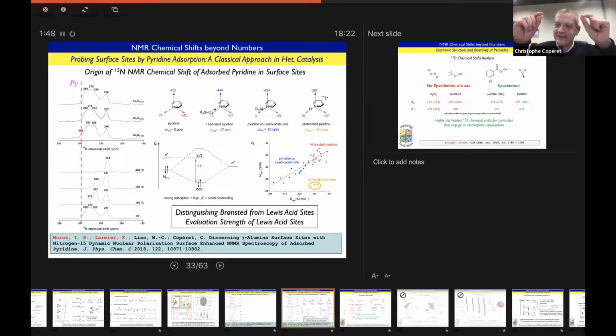It's a bit like, at the end of the day, if you look at a metal catalyst, you have a metal and the ligand. The ligand informs you about the electronic structure of the metal, but the metal also informs you about what it's doing to the ligand. And we should never forget that the ligand is often what is actually part of the reaction, as in olefin metathesis. And in some cases, the ligand is only modifying the electronic structure of the metal. So it depends on what you are looking at, basically. So I think for me, they are complementary. And it's a case-to-case basis again. Okay.